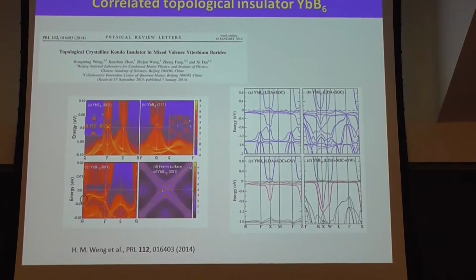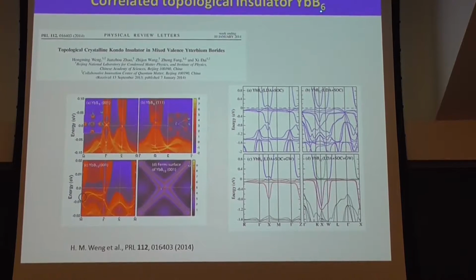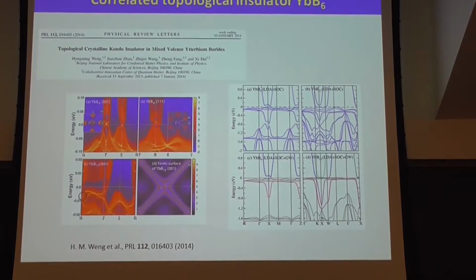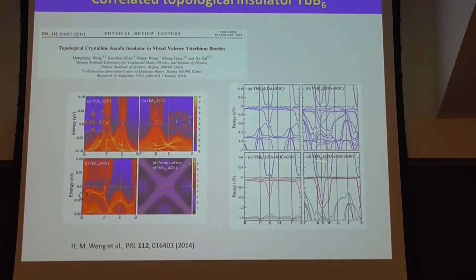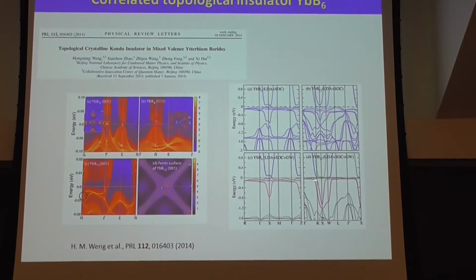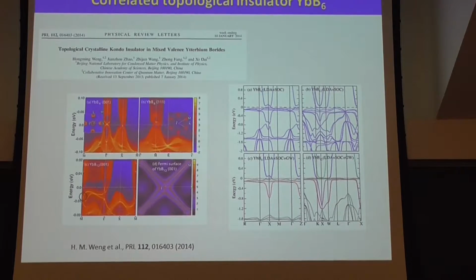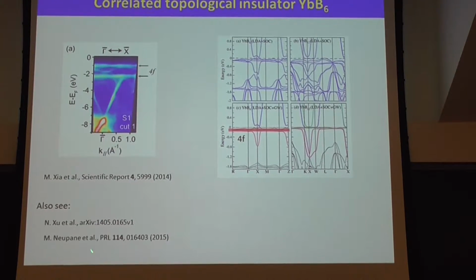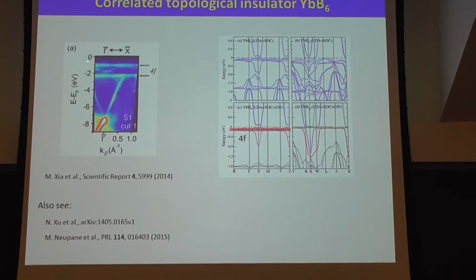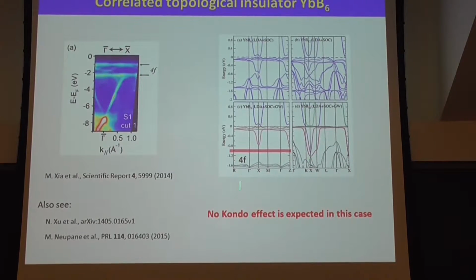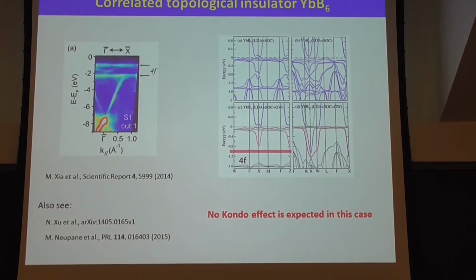Okay, then I talk about the correlated topological insulator. In the beginning, Dai Xi and Fang Zhong gave a calculation for this material that it should also be a topological insulator. But in the calculation, the f band is slightly below the Fermi level. But for the measurement, in the ARPES data, you can see the band is here, much lower than here. If the f band is too close to the Fermi level, it should be a topological insulator. But this level is around here, so no Kondo effect is expected in this case.